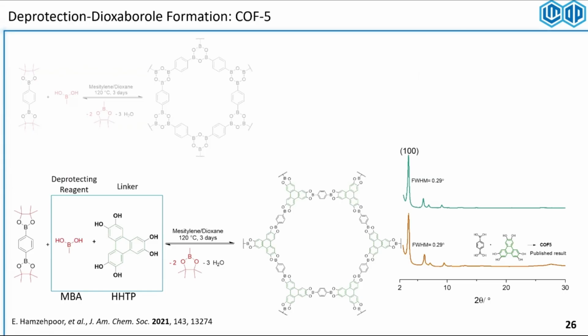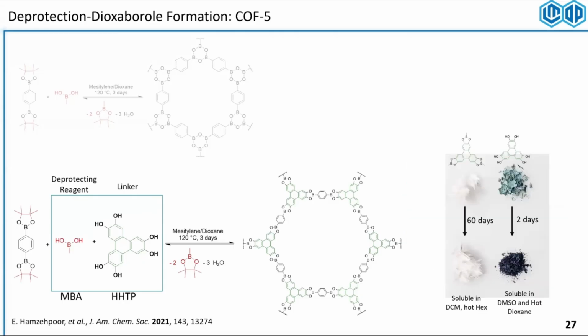So I started thinking about another type of transformation. Why not try adding another linker, and form a different type of covalent organic framework, right? And we were able to make the same thing. We identified that the phase is identical to the COF that is made from the bare boronic acids. So this methyl boronic acid transesterification works for the dioxaborole transformation as well. But that was very inconvenient to work with because now we had 3 precursors to add into a reaction vessel in small amounts. That's really difficult to do.